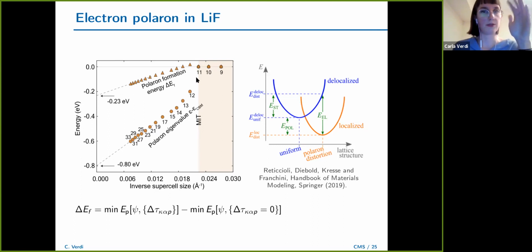Now, this number is, believe me, unfeasible in DFT. But actually, if you really wanted to converge your description of the polaron, you would need to go to much larger supercells, which is even more unfeasible. This is because the electron polaron in lithium fluoride is a large polaron. This linear behavior of the energies with respect to the inverse supercell size has to be expected. It's similar to what happens in a charged defect calculation in a supercell.